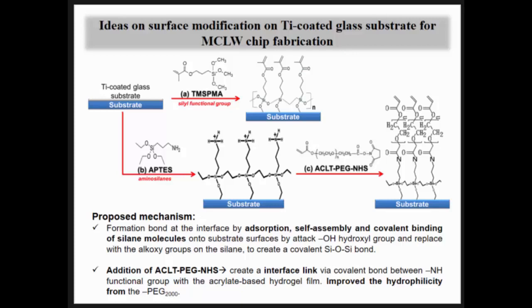However, we also want to introduce the acrylate PEG NHS during the surface treatment, because we thought that this NH group can bind with this NH, so it provides another covalent bonding. The PEG 2000 here can also improve the hydrophilicity of the substrates. My hydrogel is about 60% water, so it requires a very hydrophilic surface.